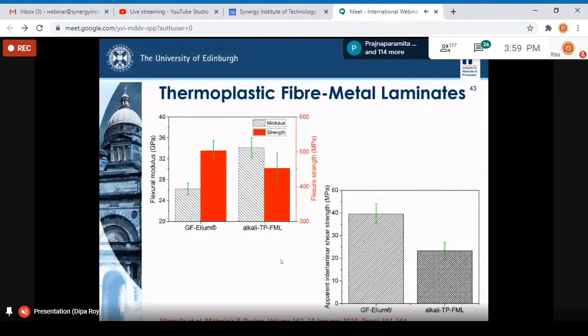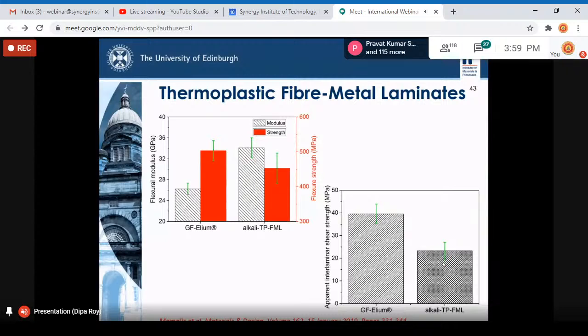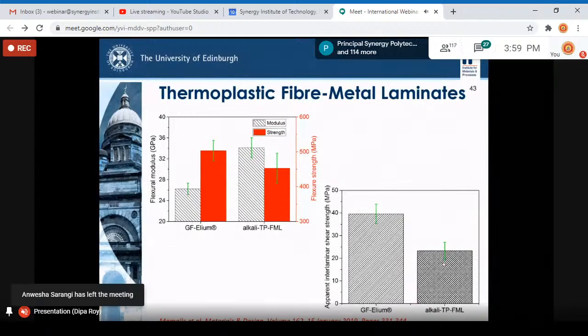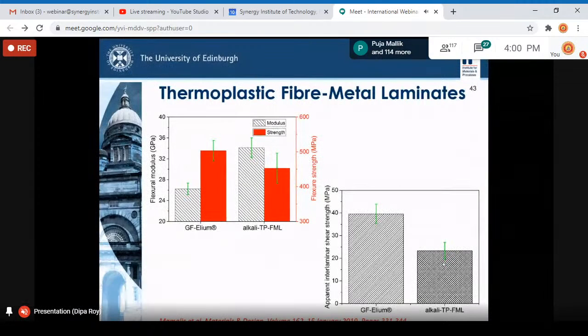And in case of interlaminar shear strength, there was quite a reduction in the interlaminar shear strength of this hybrid laminate, the fiber metal laminate. This was lower. The next step was how we can actually enhance this interfacial bonding, because the performance of the hybrid composite will be completely dependent on the interface. If the interface is not strong, then these fiber metal laminates will not be able to bear the load properly. So it is critical to have the optimum interface.